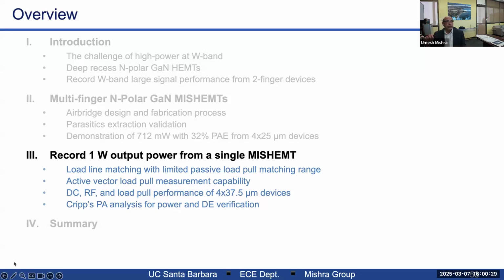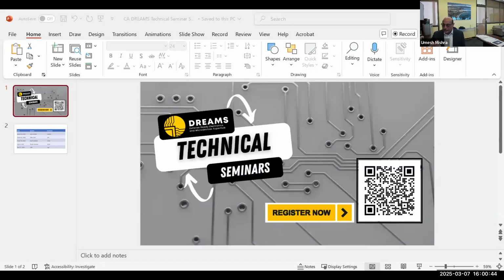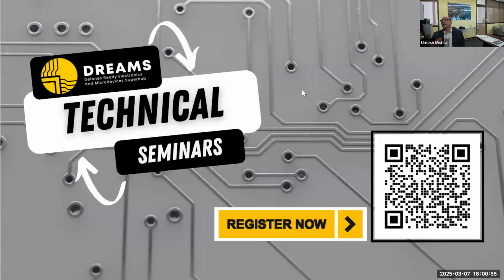So what we found, there's a fundamental issue which can be overcome by technology. The fundamental issue is when you grow GaN on top of AlGaN, you deplete the two-dimensional electron gas underneath it. So instead of adding to the 2DEG, you deplete it. So what you have to do is counter-dope it, correct? When you start counter-doping AlGaN with all kinds of things, what we found is typically that the breakdown fields in AlGaN tend to degrade.